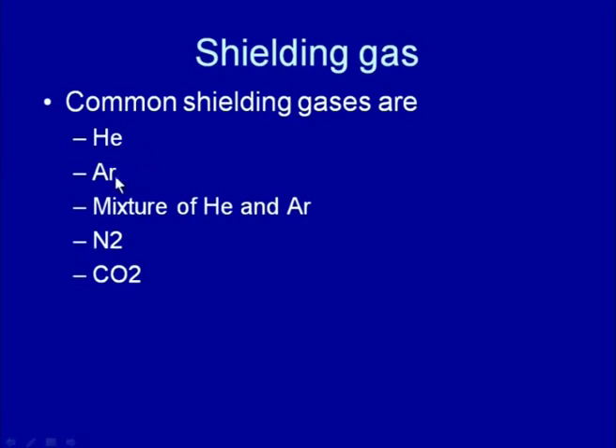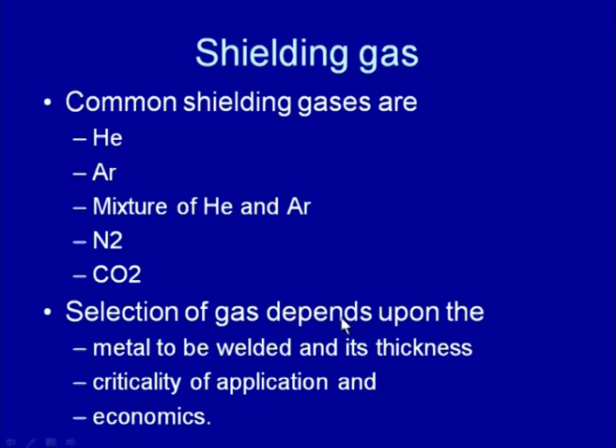You will see the kind of shielding gases which are used with the gas tungsten arc welding process. These gases are helium, argon, a mixture of helium and argon, nitrogen and carbon dioxide. If we see here, the first three gases or gas mixtures are inert gases, while the last two are active gases, but these are inactive with certain metal systems like steels. When we are welding steels while using nitrogen and carbon dioxide as a shielding gas, these help us in protecting the weld pool with a reasonable degree of protection, and further these gases are cost effective also. So, for somewhat less critical applications, the active gases are also used as shielding gases with the GTAW process.